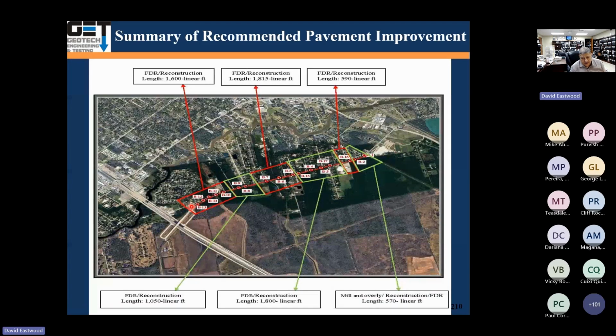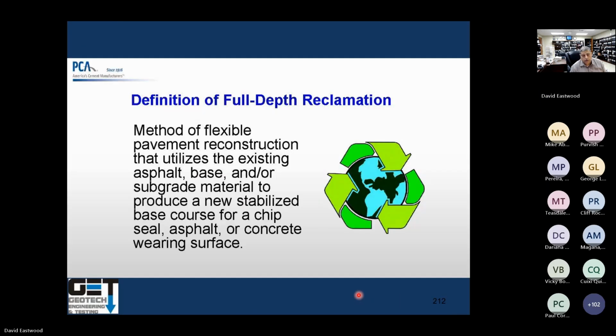So we basically divided the pavement structure along the alignment into 7 segments. This segment is for 1,600 feet. You got FDR reconstruction. This segment 2, FDR, that's full depth reclamation or reconstruction. Segment 3, FDR reconstruction, all the way to section 7. This section you can do mill and overlay because it was in good condition, or do reconstruction. Full depth reclamation. We really like full depth reclamation.